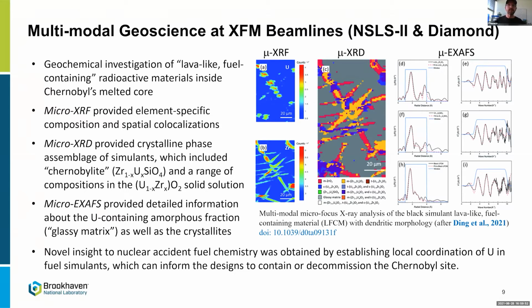Notice the XRF images, they give you element-specific maps. You're all familiar with that. Here, they're just showing us a nice co-localization of uranium and zirconium. They're not telling us they're chemically associated, but they seem spatially associated. The micro-XRD work here was actually done at Diamond in an imaging modality, and this provided the crystalline phase assemblages of the fuel simulants, which included this Chernobylite and some other compositions in the uranium zirconium solid solution.